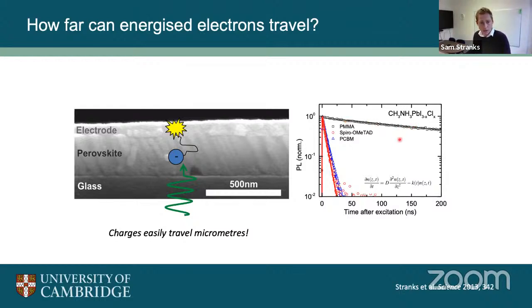And so we can model that using a diffusion equation. So these charges diffuse around, and from that we can extract how far they can travel. And what we found is that they can travel micrometers in these materials. So when we excite them here, you can see a scale bar, this is about half a micron in thickness. It means these charges can easily traverse that distance and be collected at an electrode on the other side without losing their energy to heat. So this allows us to design them in very simple ways, where they're just sandwich structures between electrodes.